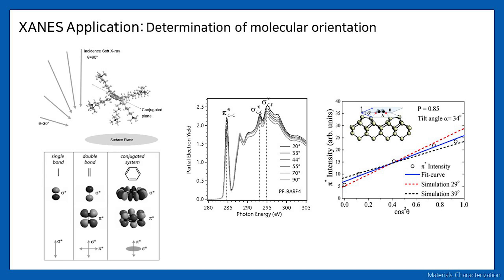Therefore, when the X-rays are investigated with varying incident angles, absorption varies depending on the orientation of the orbital in the molecule. The paper reference shows the most absorption when the angle of incident light is perpendicular to the direction of bonding, and the intensity is proportional to the scale of cosine squared theta, and the result agrees with the simulation result.